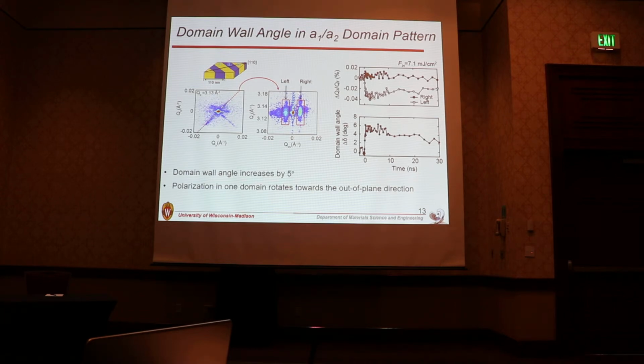And we measure the QG, the wave vector shift of the left and right domain diffuse scattering. So it's quite an interesting result because the right domain diffuse scattering is not shifted along the QG wave vectors, but the left domain diffuse scattering shifts a lot compared to the right domain diffuse scattering, which means that the domain wall angle is actually changing. So we convert this information to the domain wall angle changes and found that about 5 degrees of the domain wall angle is changed.